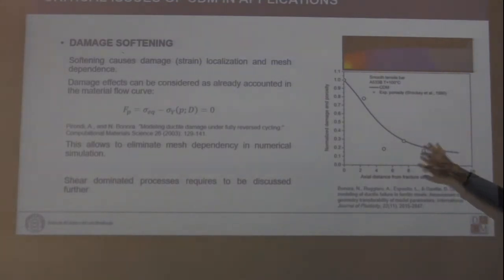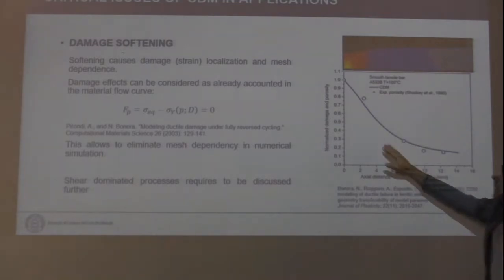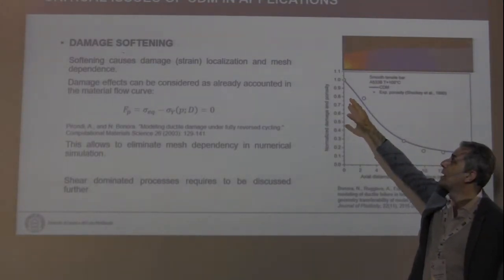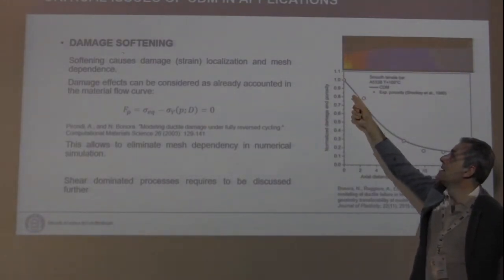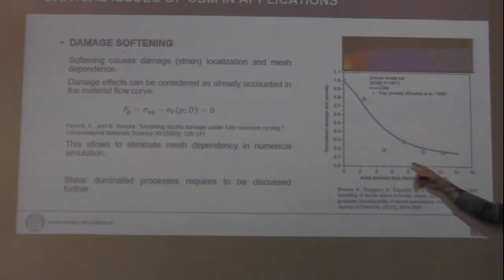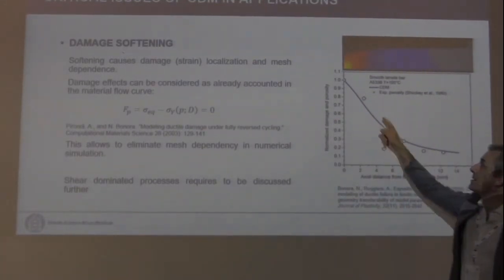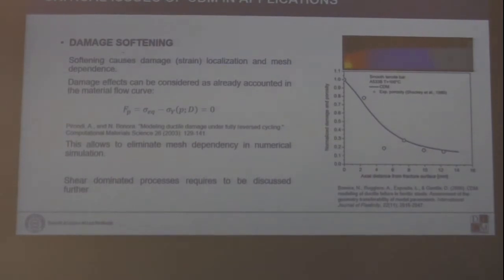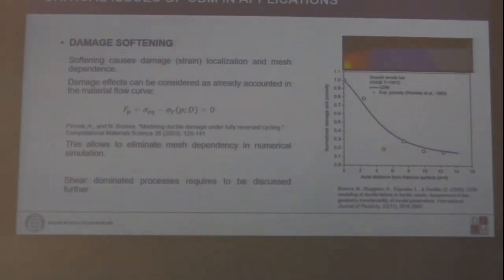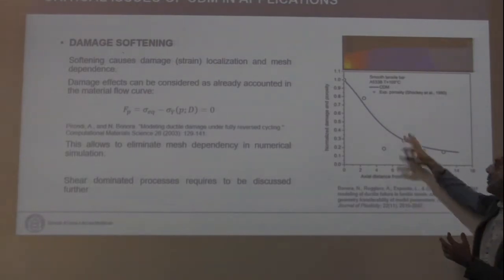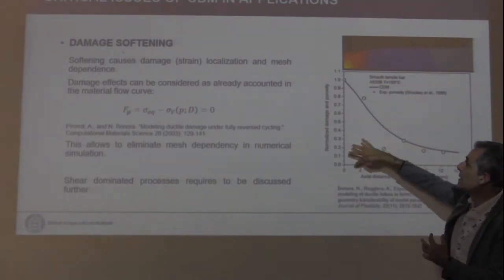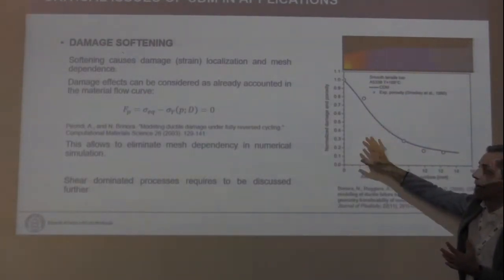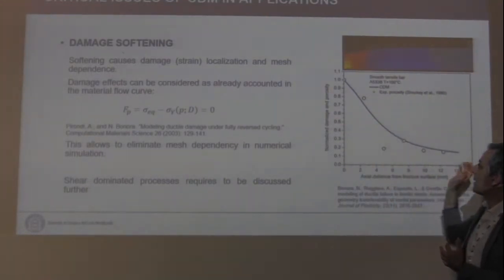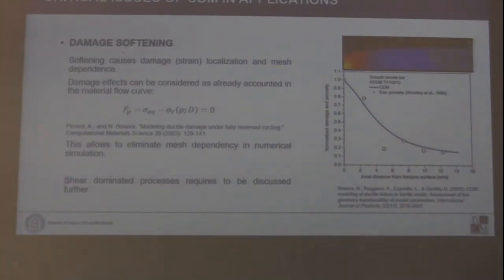In the past we made a true comparison in which we simulate damage evolution in the uniaxial bar, and this was our gradient along the axis, and these were the porosity measures that were provided by people in Los Alamos. If we normalize porosity with the critical porosity, and we normalize the damage with the critical damage, we have the same normalized graph, and so we can compare just the distribution. If you use softening, then you will have much more localized damage, which is not consistent with the experiments.